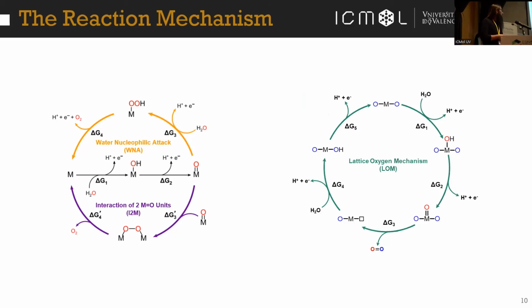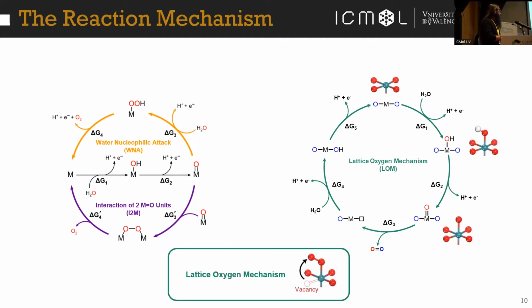This was proposed a few years ago, and this has only been seen under acidic conditions. Basically, the first 2 steps are the same, but in this case, the oxygen bond formation comes from a lattice oxygen from the metal oxide, and this forms the oxygen, and oxygen evolves, leaving this vacancy here. So this might lead to a way to the activation of the metal.